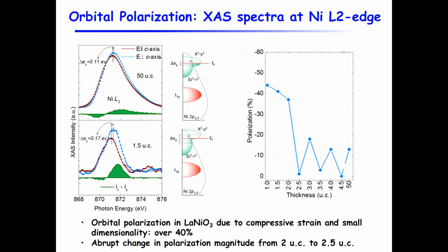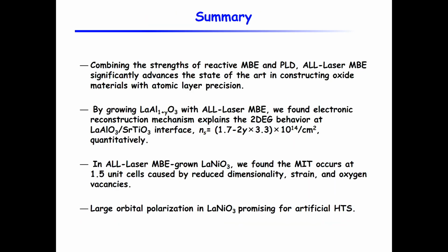We were also able to measure the orbital polarization, and we see something like 40% of polarization, which is very interesting for the next step of trying to build something like a high-TC superconductor.